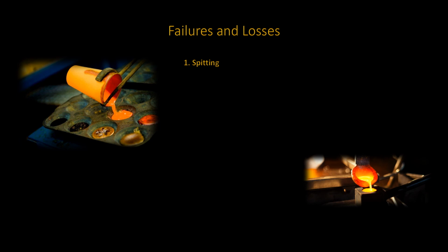At the start of the process, if air is added too quickly, rapid oxidation will cause a quick release of vapors, especially if zinc is involved. This can also happen, and it does, if your initial temperatures are too high. The resulting release of gases can and will be too rapid. Sulfur will oxidize to sulfur dioxide, and carbonates will produce carbon dioxide, and any moisture will turn to steam. Any carbonate ores will have a big effect.